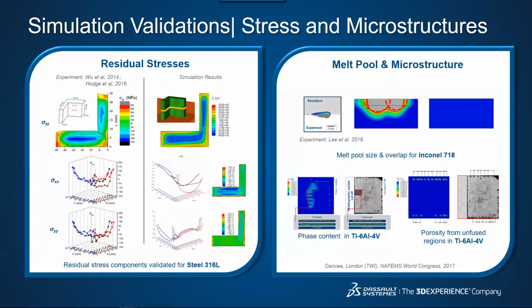And then we also have validated location-specific microstructural features, such as grain size, morphology, characteristics, and phase fractions for titanium. This was done with TWI. We were able to accurately predict phase contents compared with what TWI found in experiments for titanium 64. And we also found that we could predict porosity from unfused regions along the boundaries of these columns that they were investigating.